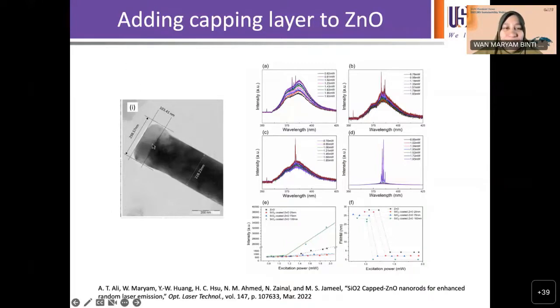So we made sure that it only covered the top part, and we noticed that when this is around 100 nanometer, or basically lambda over 4 of the wavelength of our laser, we noticed that we had superior lasing. Okay, so lasing was very good. Threshold was also very good.